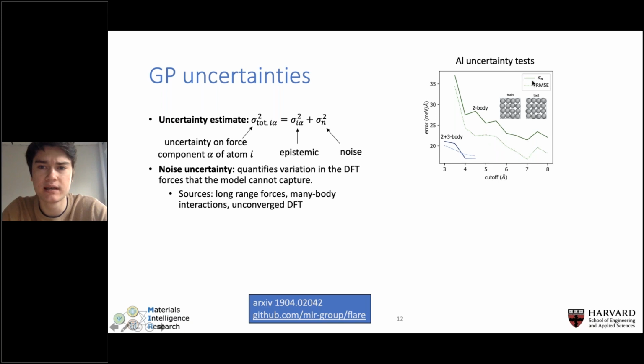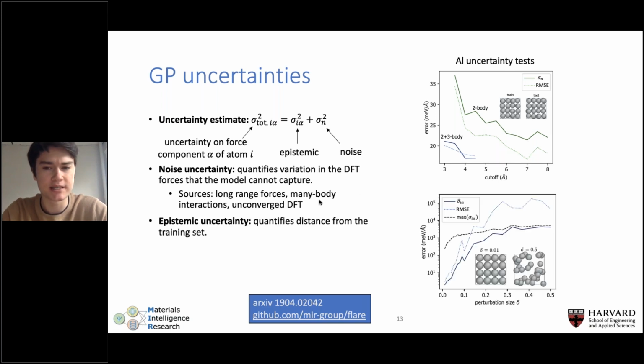But the thing to notice is that our noise parameter, which we're optimizing for each of these models, gives you an indicator of how well the model is doing. It's this kind of internal measure of model error, and it tracks the true error in this nice way. So it's giving you a measure of essentially for a given cutoff radius, how well you can expect to do without having to evaluate errors on an independent test set. So that's the noise uncertainty. The epistemic uncertainty is telling you what happens as I take atomic configurations that look really different from what the model has been trained on.